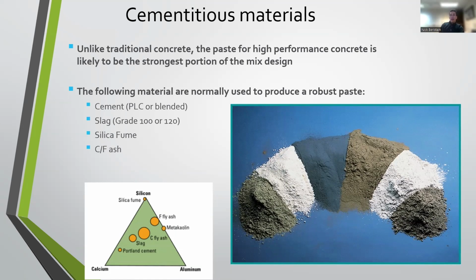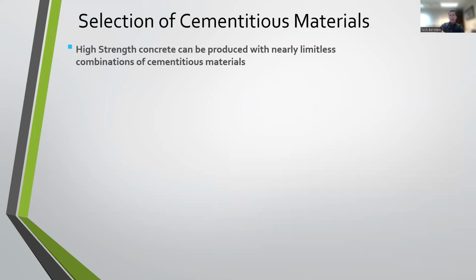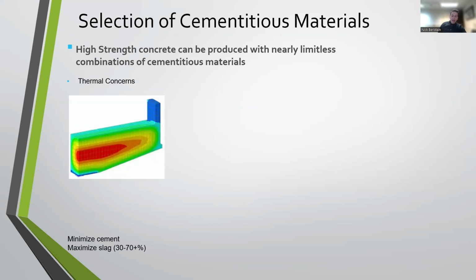To a lesser extent, we are now seeing and still continuing to use silica fume and different types of fly ashes, but those have been much more difficult to both secure and control and maintain quality supply lines for. So that has changed over the past few years, leaning more heavily on slag cement overall, as well as, and I don't mention it here, some new, more novel SCMs that are starting to come into the market. As I mentioned earlier, high performance concrete and high strength concrete can always be achieved with numerous different options in terms of specific material choices, and it all is really dependent on the type and requirements of the project.